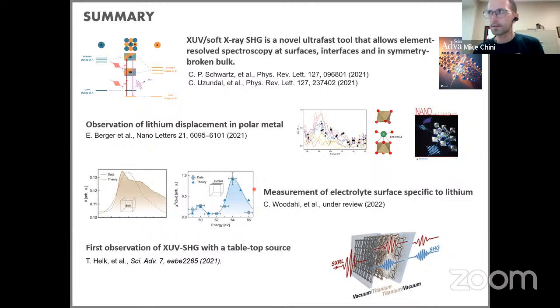So in this case, if you were to excite some kind of time-dependent structural phase transition where it goes from a symmetric to an asymmetric state, then you might expect that you see more of the surface when it's in the symmetric state, and then as symmetry breaks, you would see more of the bulk. Yeah, okay, yes, that's interesting.